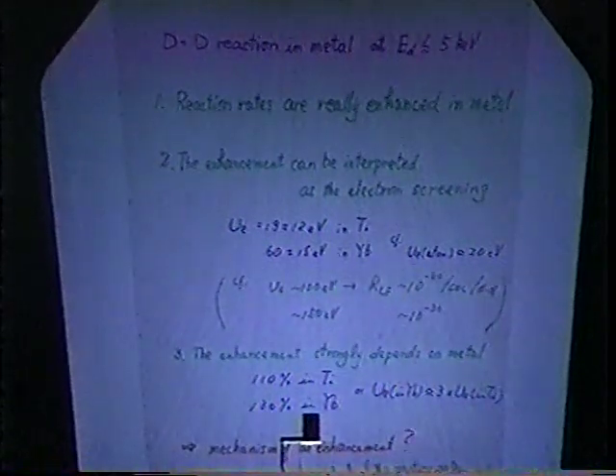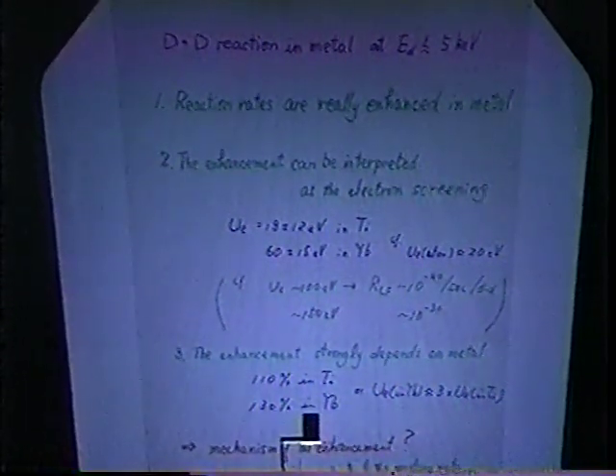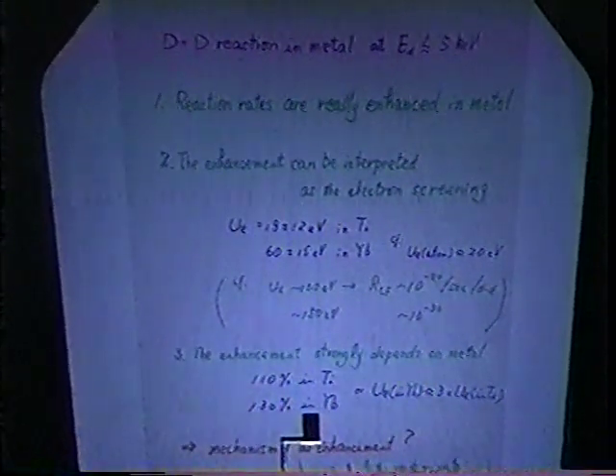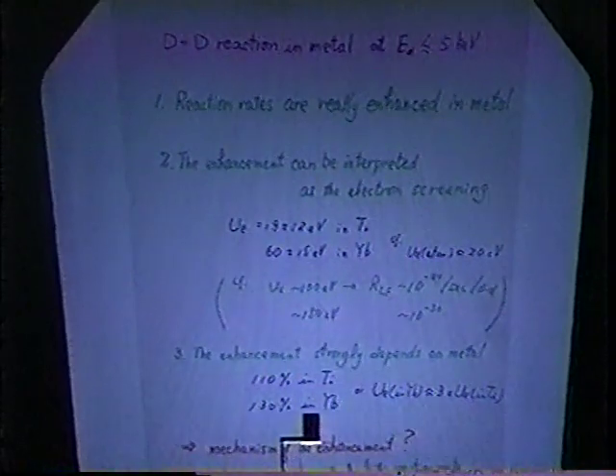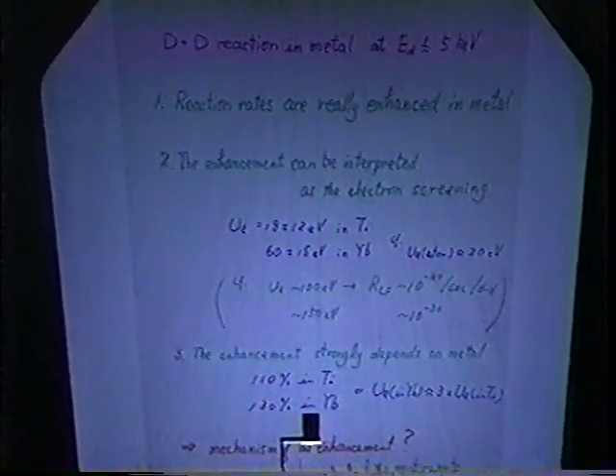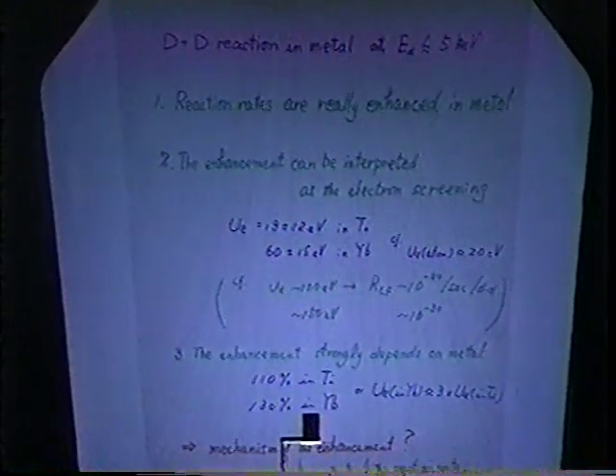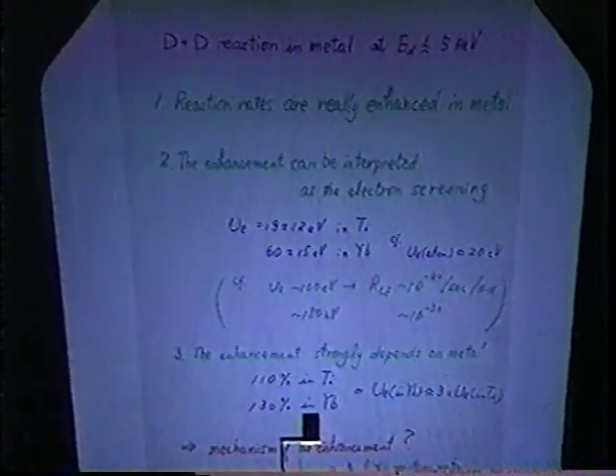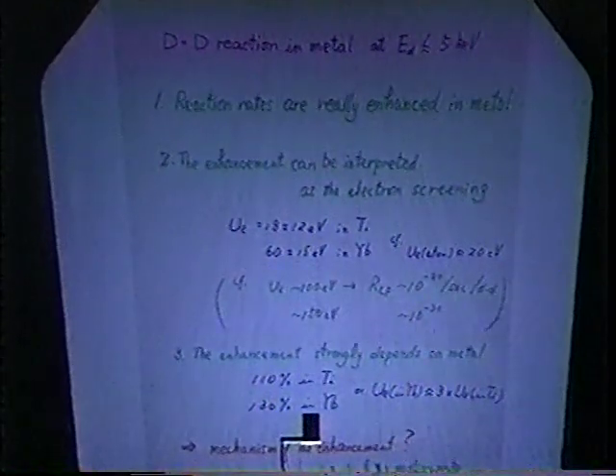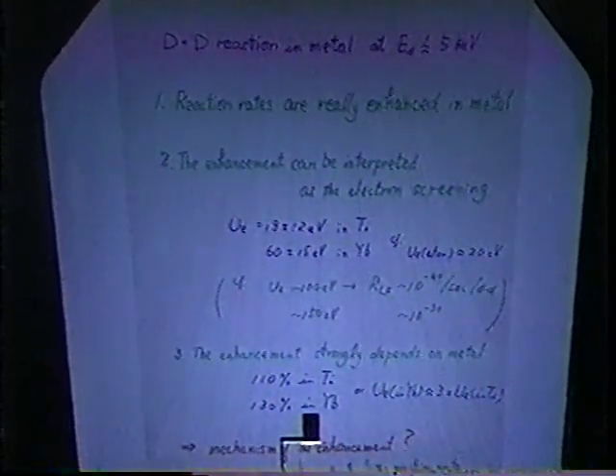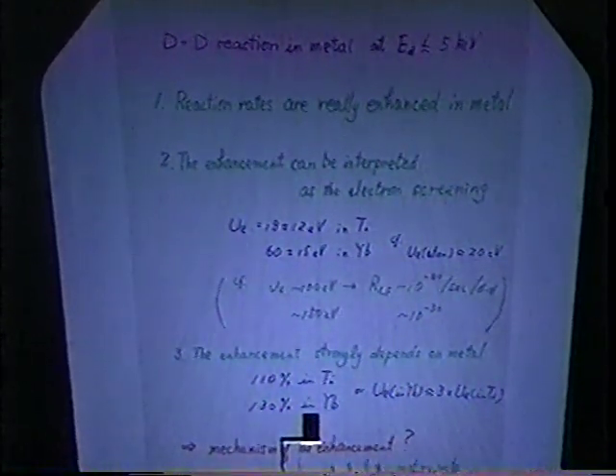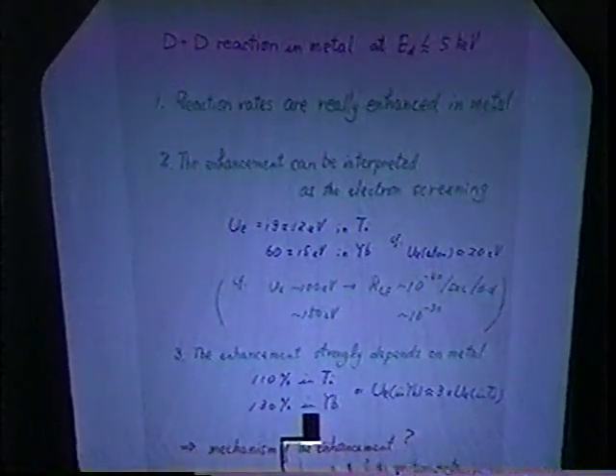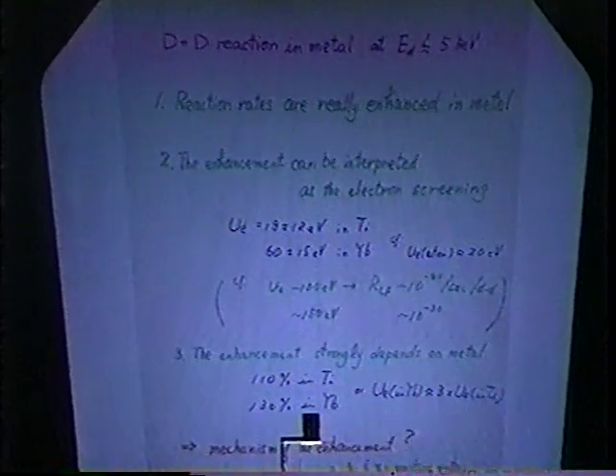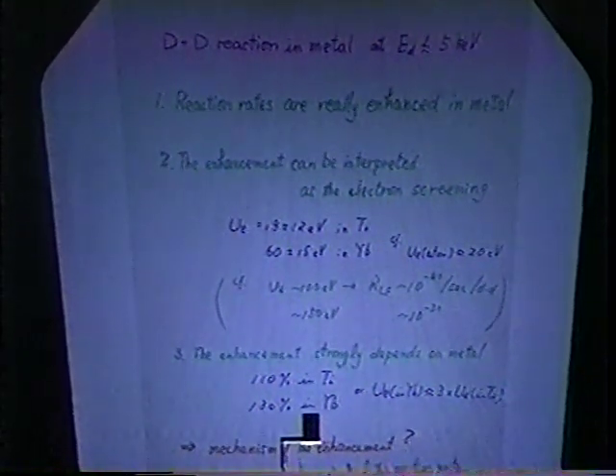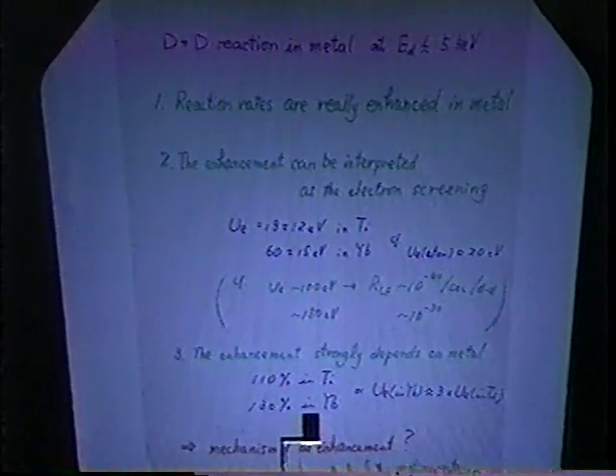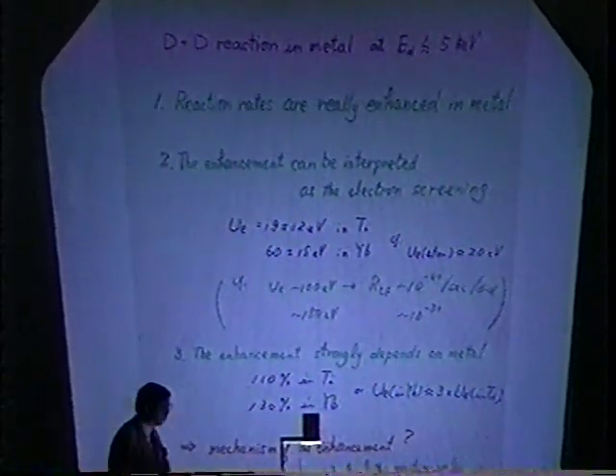But it should be noticed here, in the atom case, the screening potential is something like 20 electron volt. This is the experimental result for the atom case. And also, this screening potential, of course, cannot explain cold fusion, because if we require a cold fusion rate, for example, this rate, then we need a 100 electron volt screening potential. And also, if we require this order, we need this kind of screening potential.